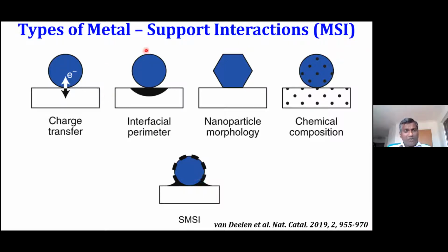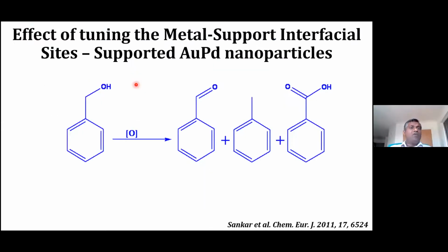So to start with, I will give you an example of how, by tuning the metal support interfacial sites, we can tune the selectivity of a particular reaction. For this, I'm going to take an example of a simple benzyl alcohol oxidation. The catalyst used here is supported gold palladium nanoparticles. We use oxygen as the oxidant, with solvent-free benzyl alcohol. Here the product of interest is benzaldehyde. However, we get a large amount of toluene in this reaction.